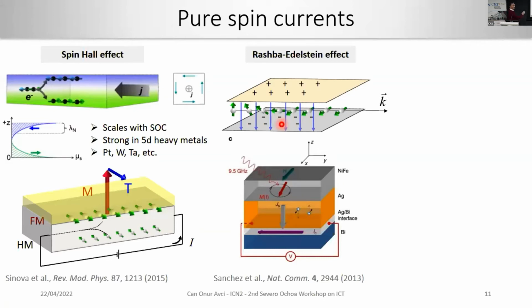But the spin Hall effect is not the only effect. So there are other alternatives. For instance, the Rashba-Edelstein effect, which is using the broken inversion symmetry at the interface that basically polarizes the charge current going through. And this occurs at metal-metal interfaces or metal-oxide interfaces or even oxide-oxide interfaces. So due to the symmetry breaking, you have a built-in electric field. And due to the relativistic effect, a charge current going through the electric field feels a magnetic field and it tries to align to it. So you can also harness this kind of spin accumulation in devices.